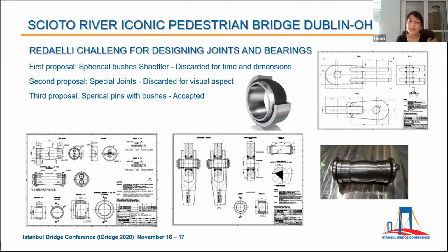Subsequently, Redaelli designed and proposed a special joint between the socket and the anchor plate. But this solution has been rejected because of visual and architectural concerns. And finally, Redaelli designed and manufactured a set of pins that you see in the lower right corner with a spherical shape in high strength stainless steel, which bear against a spherical isolating washer. And this solution has been accepted because it had minor modification in the structure and totally solved the problem.